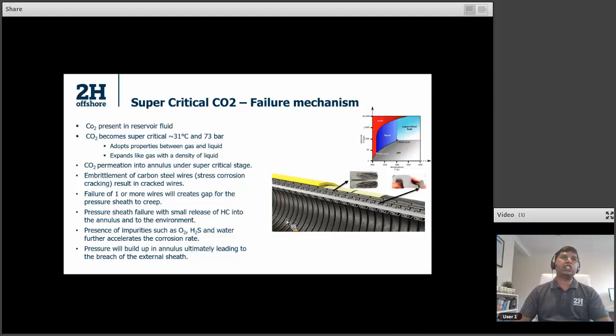CO2 in its supercritical stage enhances the embrittlement of carbon steel by stress corrosion cracking mechanism. And failure of one or two of these wires would make the pressure sheath creep into the annular space, resulting in small ruptures. And once these ruptures are evident, you see more hydrocarbons flowing into the annulus, and with the reservoir fluids directly penetrating into the annulus, you'll see more and more accelerated corrosion due to the presence of other impurities such as oxygen and hydrogen sulfide and water. And eventually, when there's more pressure than the annular structure can sustain, you will have breach of your outer sheath, resulting in loss of hydrocarbons to the environment.